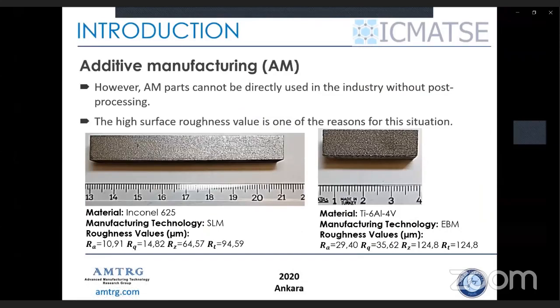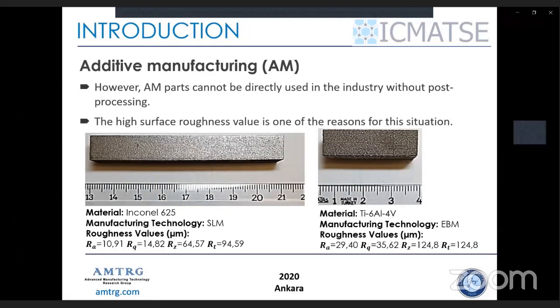However, these parts cannot be directly used in the industry without post-processing. The high surface roughness value of these parts is one of the reasons for this situation. As you see here, there are two samples which are produced by two different additive manufacturing techniques. The material of the first part is Inconel 625 and it is produced with SLM technology, which is selective laser melting, and the material of the second part is a titanium alloy and it is produced with electron beam melting technology. As you see, the surface of these parts are very rough and these parts cannot be accepted in the industry without post-processing.